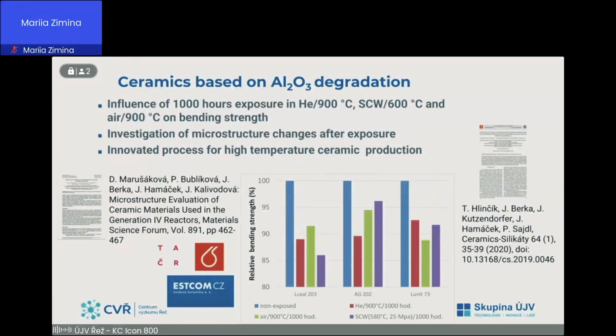So, within the project we also tested the mechanical properties of selected ceramic materials based on corundum or mullite. The ceramic materials were exposed in different environments, among others in high temperature helium. In some materials, some differences in bending strength were observed after exposure, but the differences were not significant.